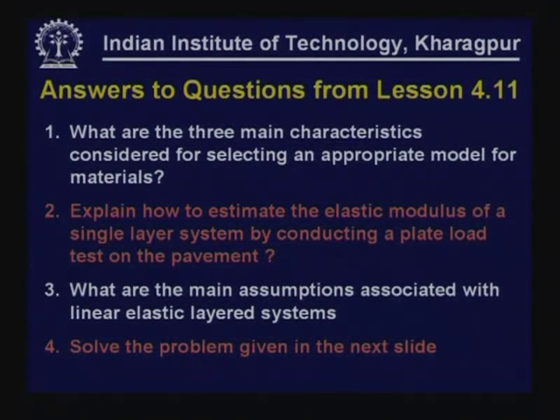Explain how to estimate the elastic modulus value of a single layer system by conducting a plate load test. If you conduct a rigid plate load test, measure the surface deflection, and know the value of contact pressure P and radius of load contact area A, then using the expression for a rigid plate: surface deflection = 1.18·P·A/E, where E is the modulus of the material. P is known, A is known, deflection is measured, and we can estimate the modulus value.